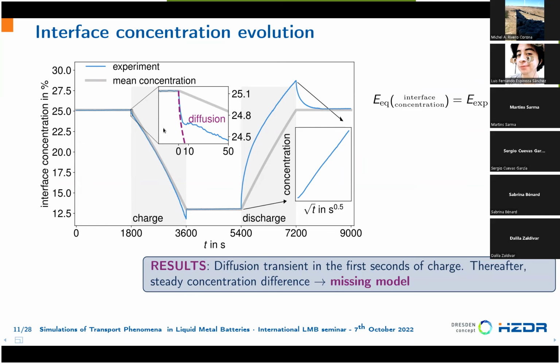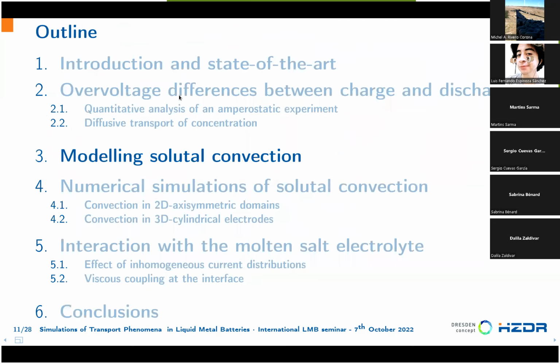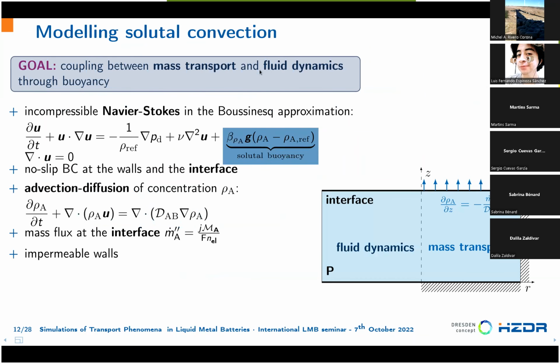So now we will move to charge and try to understand what is taking place here at the beginning of the charge phase. And to do that, we need to model solutal convection. So we need to couple mass transport and fluid dynamics through buoyancy. We solve incompressible Navier-Stokes in the Boussinesq approximation, including these additional terms that take into account the buoyancy. This is the solutal expansion coefficient, and this contains the concentration field. And then we also advect and diffuse the concentration field.